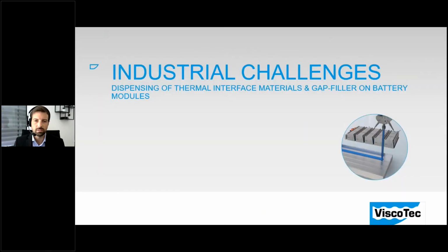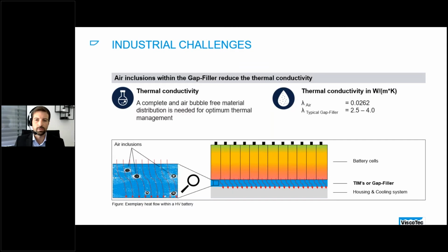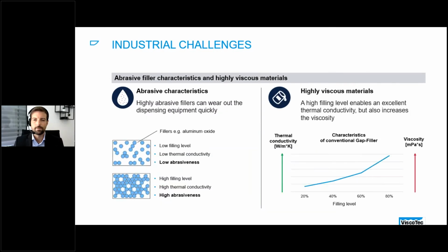But now, what are the industrial challenges when it comes to dispensing of thermal interface materials? For an optimum thermal management, a complete and air bubble-free material distribution is needed. So air bubble-free is the word here. As illustrated below, as soon as the gap filler contains air inclusions, the thermal conductivity gets negatively affected. A look at the thermal conductivity properties of air compared to a standard gap filler shows the huge difference. The thermal conductivity of a gap filler is at least 100 times better, and any air entrapment acts like a kind of isolator in this process. Next slide, please.